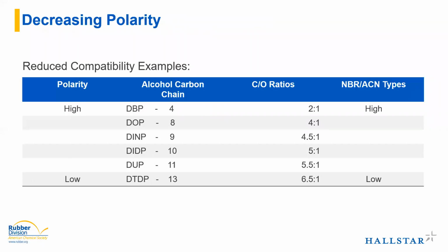Just to further illustrate how we calculate and estimate, we literally just count the carbons and oxygens present in the molecule and look at that number as a ratio. DBP with very short carbon chains only has 4 carbons present for every 2 oxygens. So we have that 2-to-1 ratio, and that's considered a high polarity material. Going all the way up to the tridecyl with the 13 carbons to every 2 oxygens, you're at a 6.5-to-1. That's a low polarity material with a high carbon to oxygen ratio.